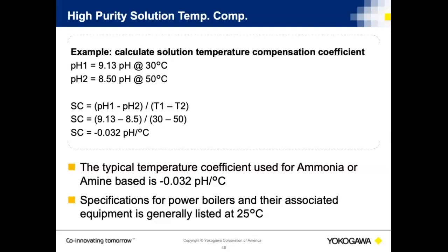in your calculation below. All you do is throw it into the equation, and you end up with pH1 minus pH2 divided by temperature 1 minus temperature 2. And you notice you end up in this example at minus 0.032 pH per degree C. And you get the added benefit that it's comparing the value to the known value at 25 degrees C.